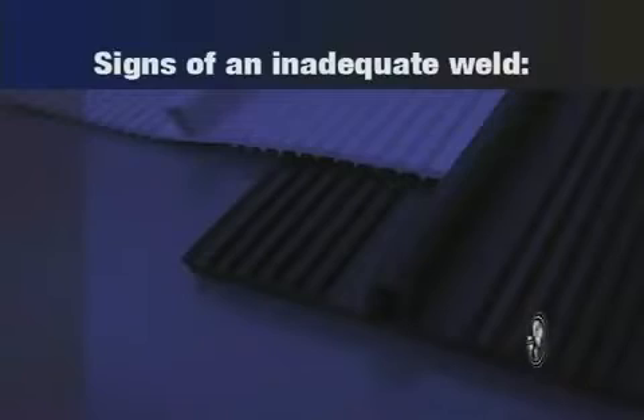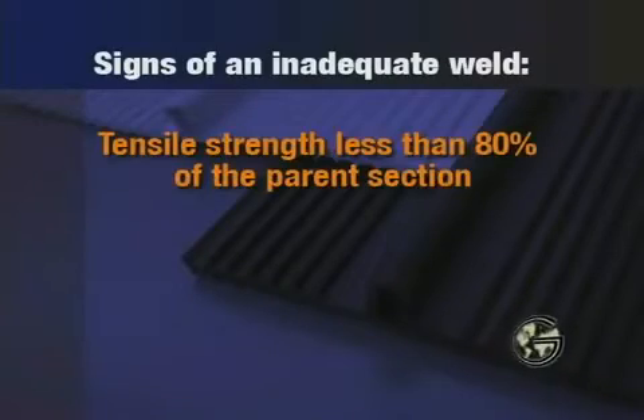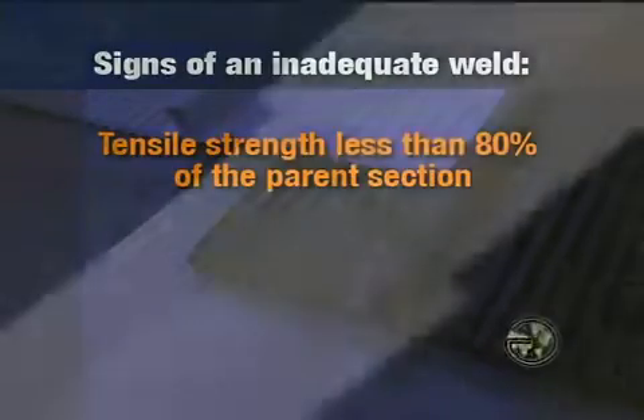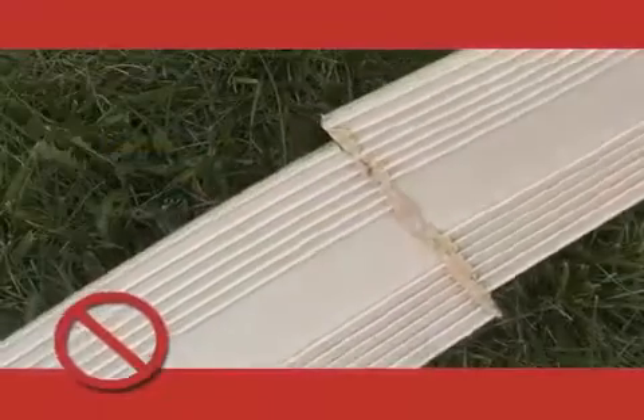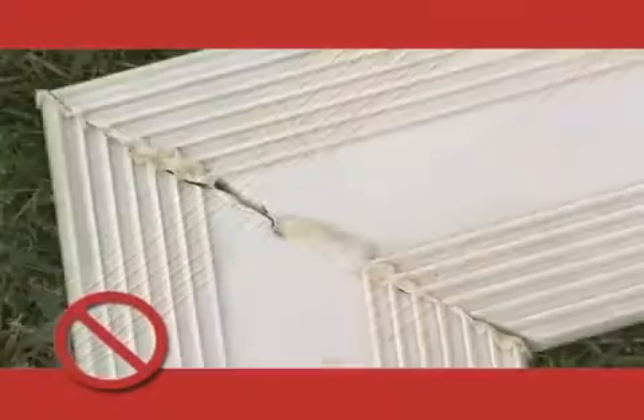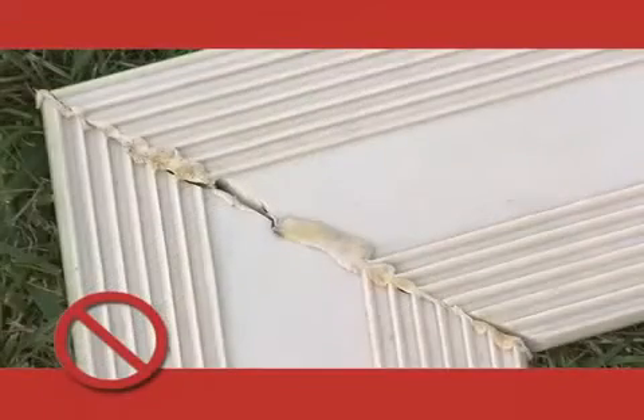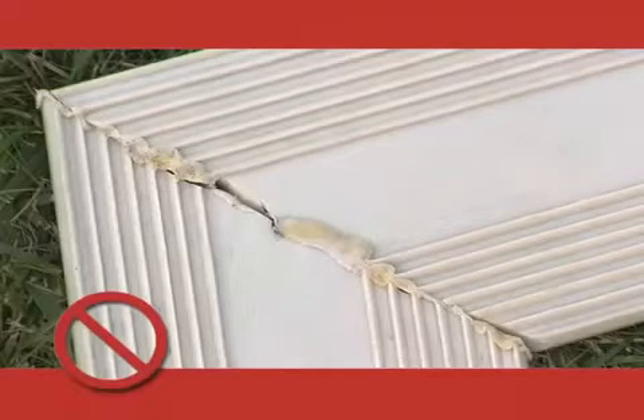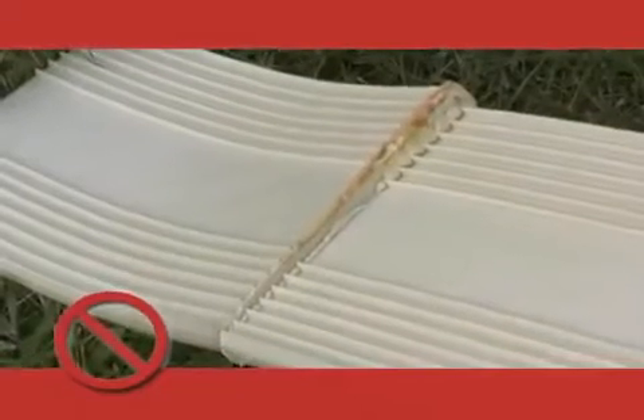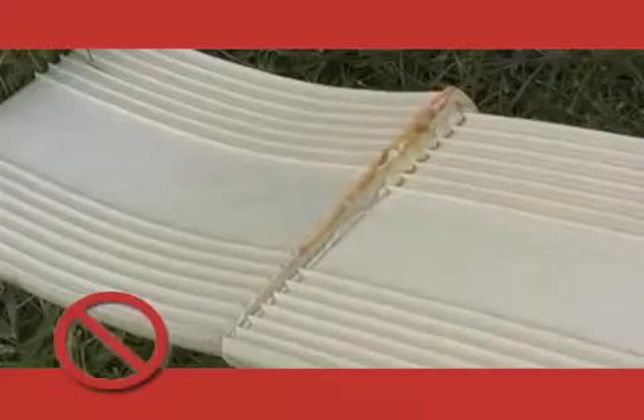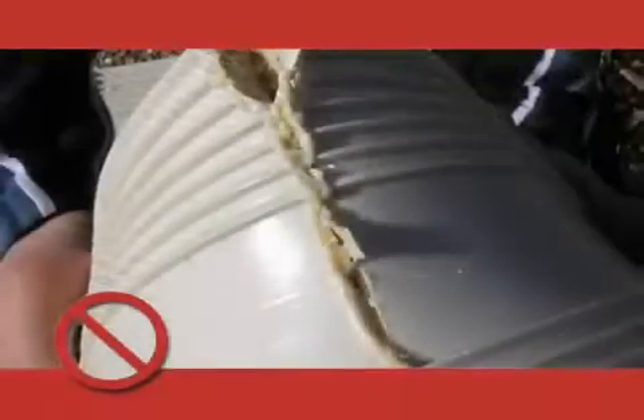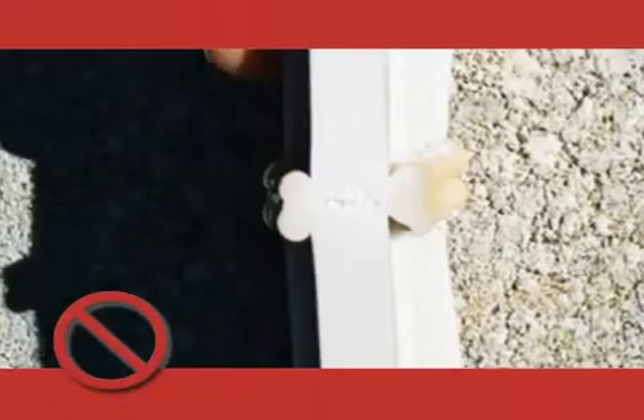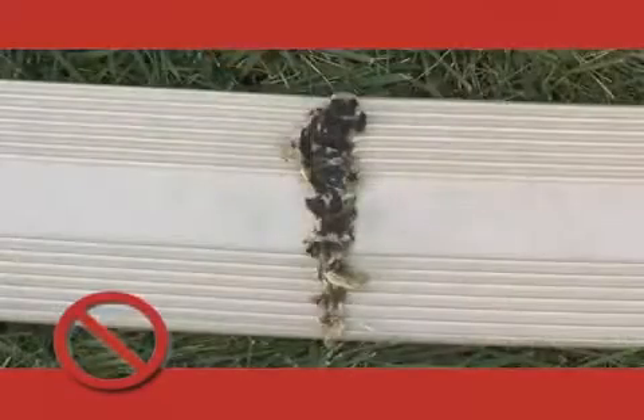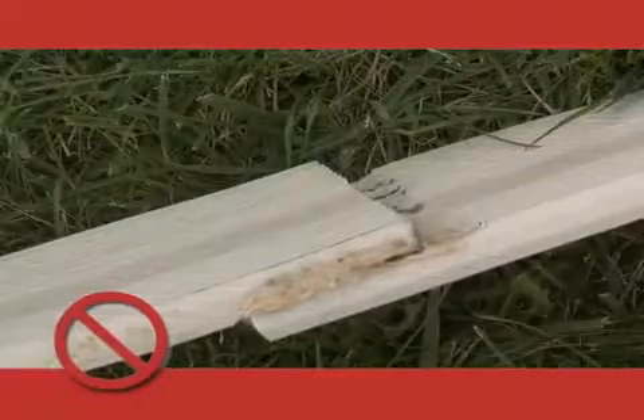Signs of an inadequate weld include tensile strength less than 80% of the parent section, misalignment of center bulb, ribs, and end bulbs, bond failure at joint deeper than 1/16 inch or 15% of the material water stop thickness, misalignment which reduces the water stop cross-section greater than 15%, visible porosity in the weld, visible signs of splice separation when a cooled splice is bent at a sharp angle, charred or burnt material, and an overlapped weld.